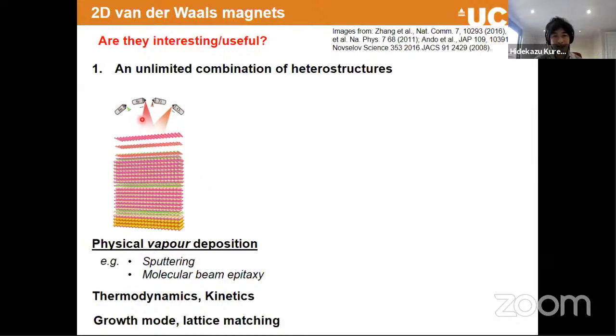And here, I just want to look at the dynamics. Normally, when you do that, you sputter, let's say, a target, and you decompose everything into atoms or dimer molecules, and then that can run on a substrate or underlying layer, which has local thermodynamics and kinetics. That's the growth mechanism, and that can create some constraints. For example, you cannot make a very flat surface if you want to grow metal on a semiconductor or insulator, because of different wetting.